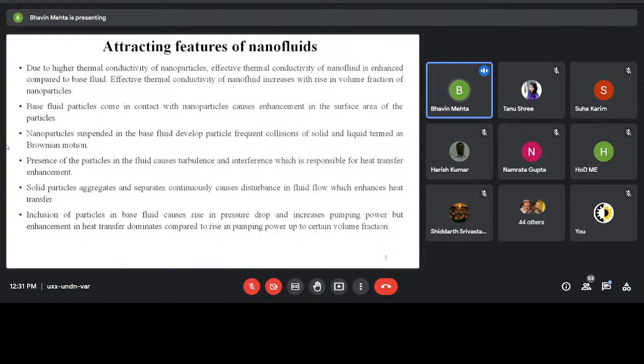But the rise in the pumping power will be lesser compared to the augmentation in the heat transfer. So ultimately, up to a certain volume fraction, the nanofluids will show overall good performance compared to conventional working fluids. And at last, the nanoparticles possess good absorption and extinction coefficients. So basically, it also finds its suitability for direct absorption type solar collectors.